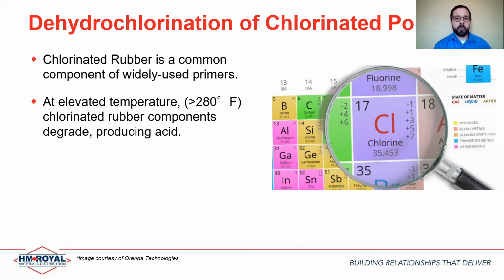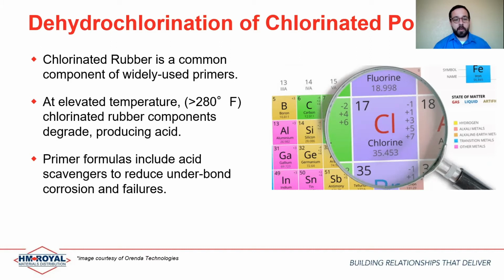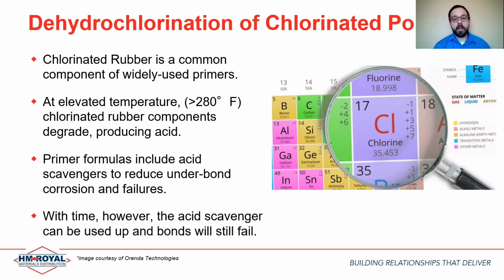So now that you know that fact, why does that matter? At elevated temperatures, let's say north of 280 degrees F, you're going to start to see the chlorinated rubber components degrade, and that's going to produce hydrochloric acid in the system. That sounds bad. The good news is these primers are formulated to include scavengers to reduce underbond corrosion and failures as a result of this production of acid. The bad news is that with time, the acid scavenger is used up, and these bonds over extended periods in exposure at these temperatures or in some fluid environments will still fail.